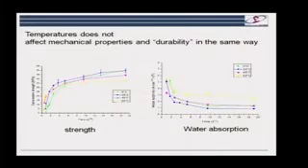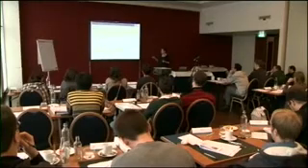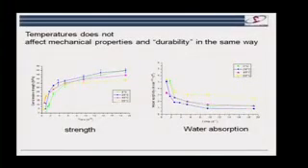What is so important is that when you look at various properties, you see something rather strange. So if we look at this development of strength here, you see that at 1 day, for example, the one that's hydrated at 60 degrees has a much higher strength than the one hydrated at 20 degrees. Well, you'd expect that because the reaction's faster. You've got much more reaction. But what you don't expect is what you see over here, which is at quite long times, the material that's hydrated at 60 has a significantly lower strength than that hydrated at lower temperatures.